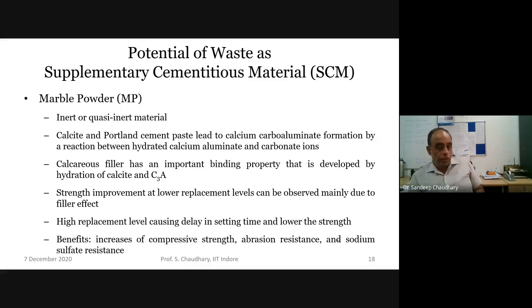And of course, another important material which people have been using, particularly in Rajasthan, is marble powder. It's an inert or quasi-inert material, and it has been used as a fine aggregate, but people are trying to see its use as a supplementary cementitious material. What happens is that calcite and Portland cement paste lead to calcium carboaluminate formation, which has important binding properties, developed by hydration of calcite and C3A. So there is a strength improvement at low replacement levels, observed mainly due to the filler effect. But high replacement levels cause delay in setting time and lower the strength.